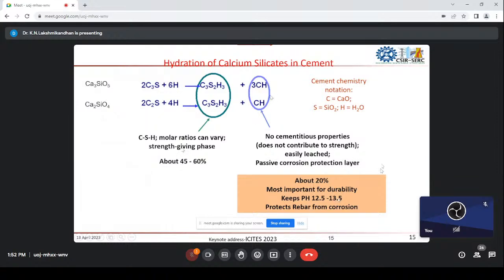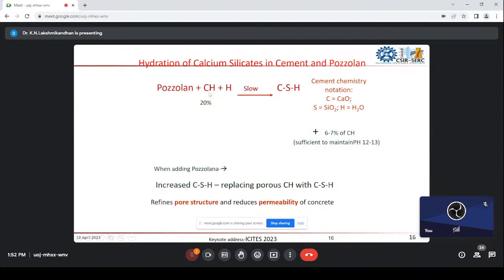But what is the percentage? Normally, to maintain this pH we need around 10 to 15%, around 13% normally. The 13% presence of calcium hydroxide can keep the pH around 12.5 to 13.5, so the remaining 7% we can effectively utilize. In that way, for developing a dense cement, we minimize the cement content to less than 450 kg per meter cube and utilize pozzolanic material. Pozzolanic materials react with the calcium hydroxide in the water, which again gives the pH. This way we can utilize around 6 to 7% of the calcium hydroxide for developing the pH itself. Overall, the system gives a denser medium, and it will not permit chloride or carbon dioxide to enter, which normally initiate the corrosion of steel.